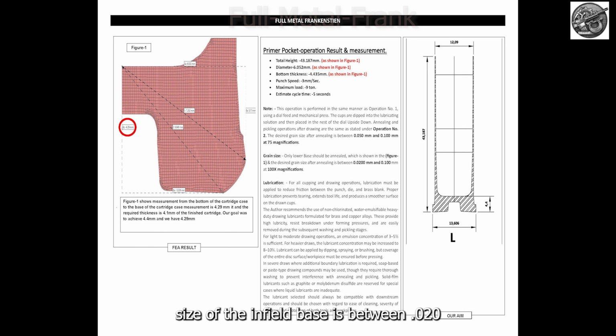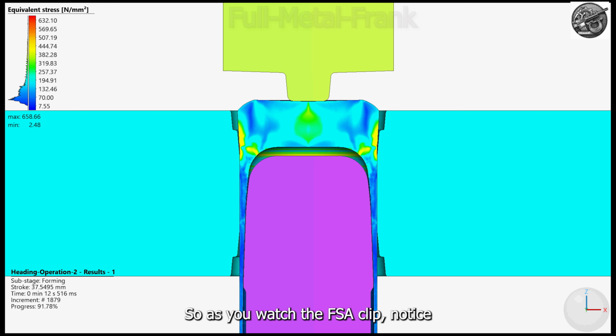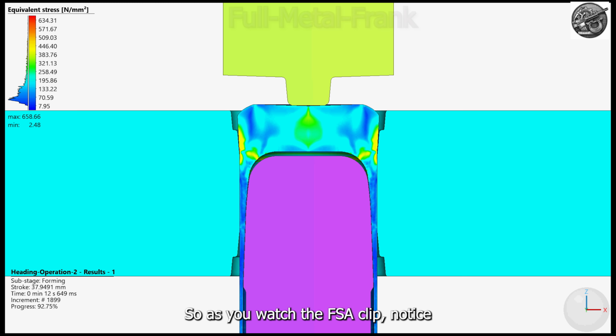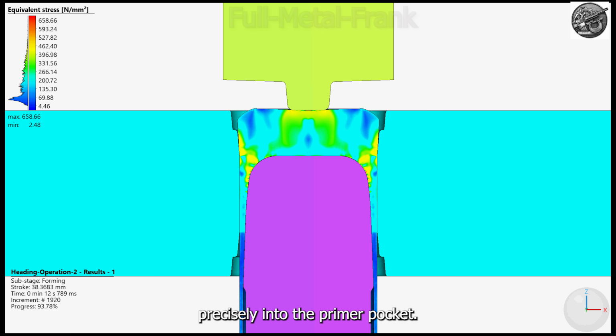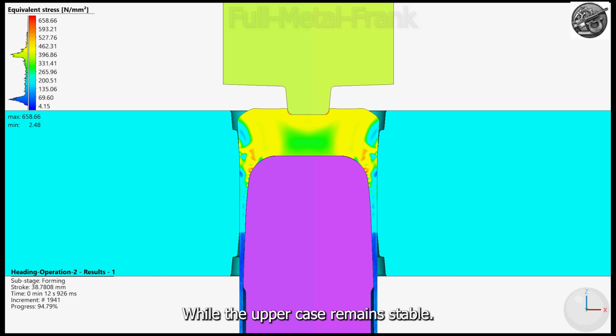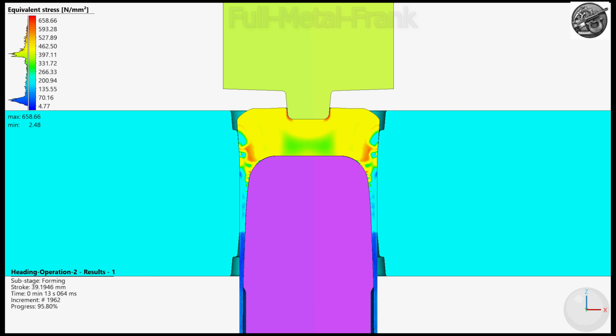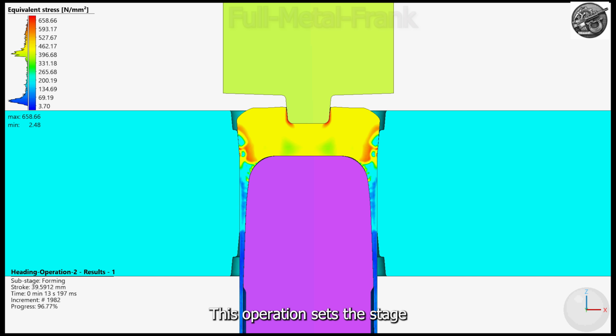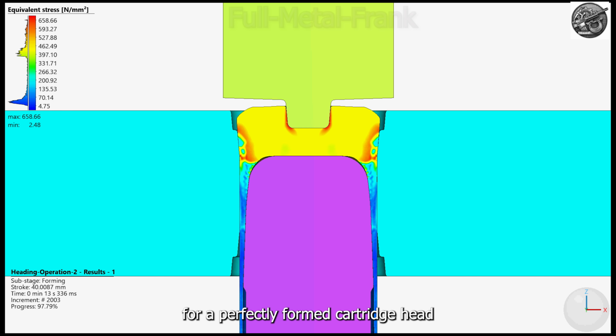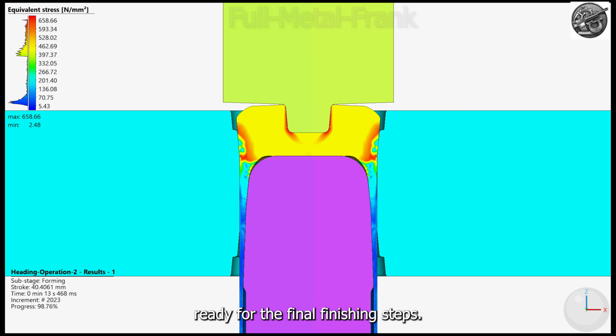Target grain size of the annealed base is between 0.020 and 0.10 millimeters at 100x magnification, ensuring the material is soft enough to form the pocket without compromising strength. So, as you watch the FEA clip, notice how the base deforms precisely into the primer pocket while the upper case remains stable. This operation sets the stage for a perfectly formed cartridge head ready for the final finishing steps.